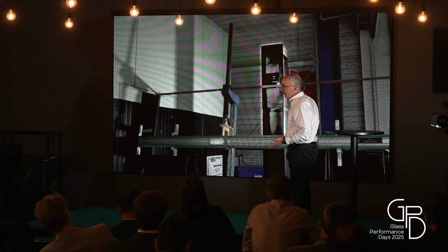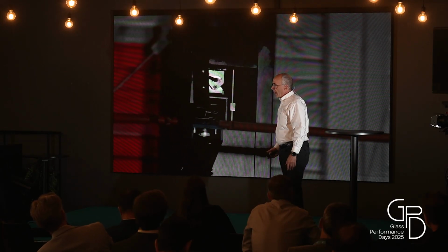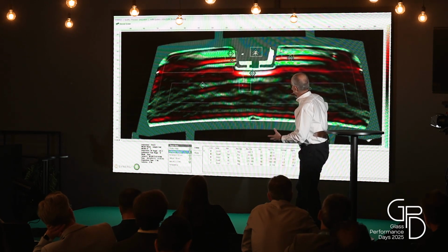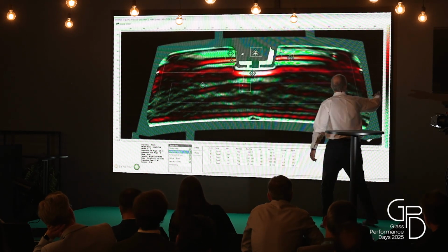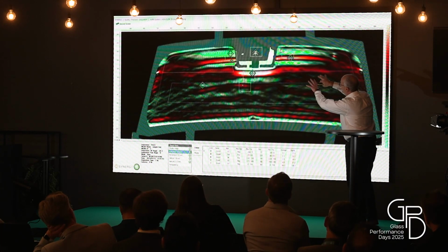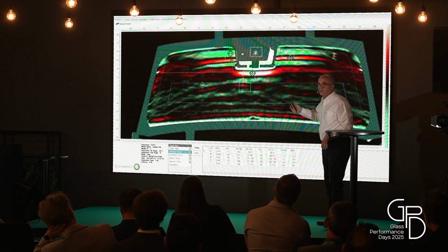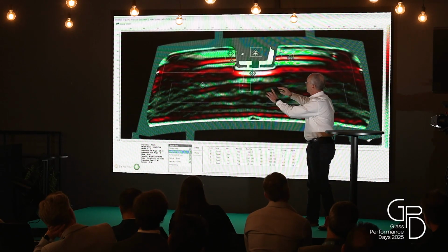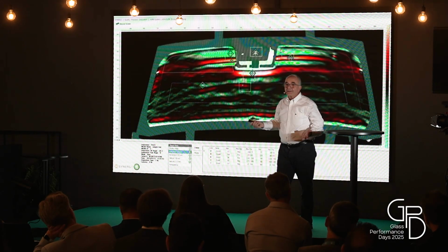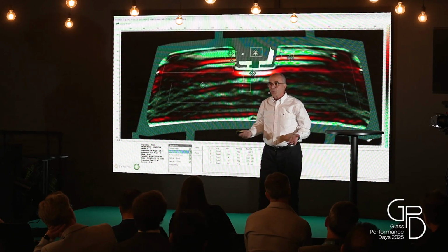So the machine decides what it wants to do. And your end result is a mapping. So you have the intensity, so you know your number of millidiopters on the scale, and you can see where your hot points are, and you can determine different zones for the driver, for the cameras, for everything. So that is really mastered in the automotive industry.